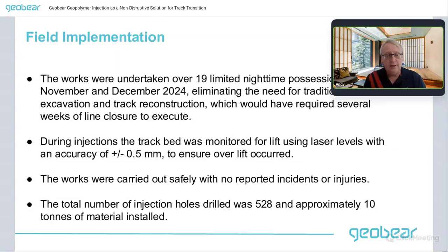And the total number of injection holes drilled was 528, and approximately 10 tons of material were put into the embankment. And the key thing here is this has all been done at night in very short possessions, maybe less than 5-hour possessions, to actually get the work done. So there's literally no impact on the operation of the railway during this treatment.